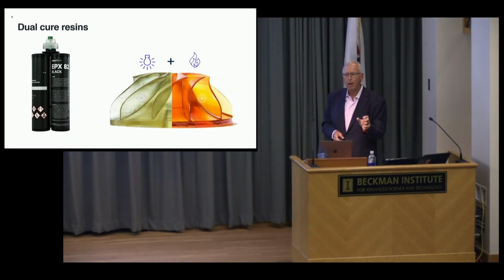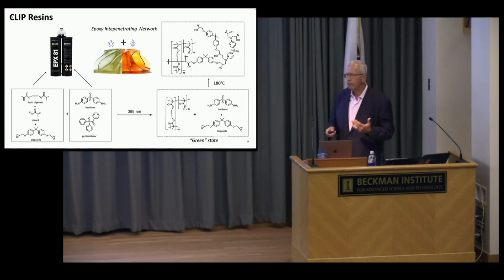And so what we did is we combined and did orthogonal chemistry. Just like Carolyn Bertozzi just got the Nobel Prize in orthogonal chemistry for doing chemistry in a cell without screwing up a cell, this is orthogonal chemistry in the printer. I'll give you a couple examples. Let's talk about epoxy chemistry. Epoxies are diepoxides and diamines. And we added a free radically curable system and a photoinitiator. And we keep these two separate so we could ship them off because you don't want the amines and epoxies together. When you buy an epoxy glue, you go to a grocery store, it comes in 2 tubes.